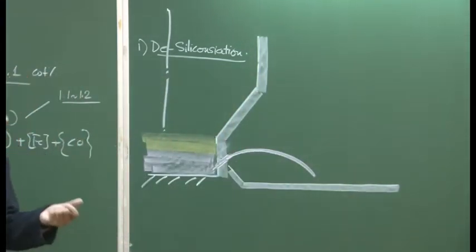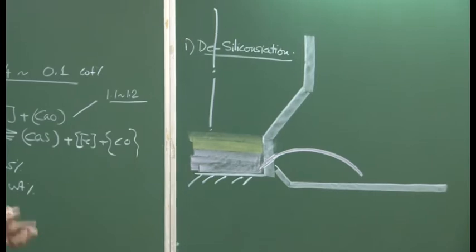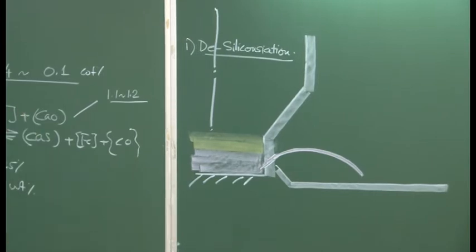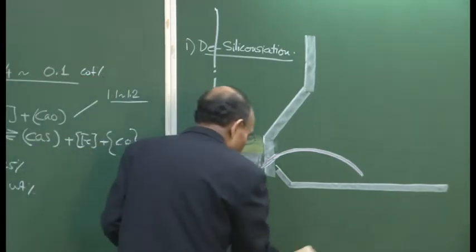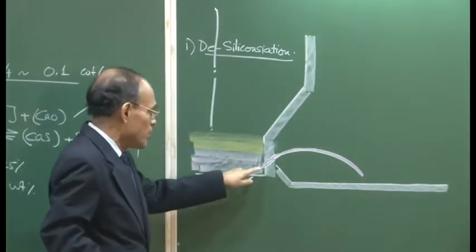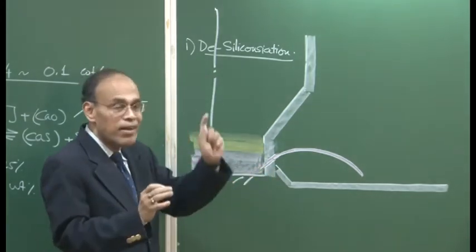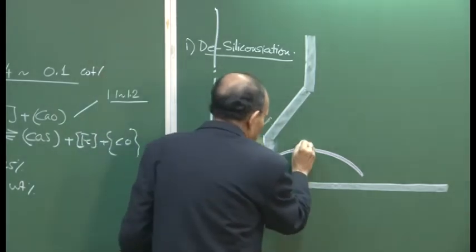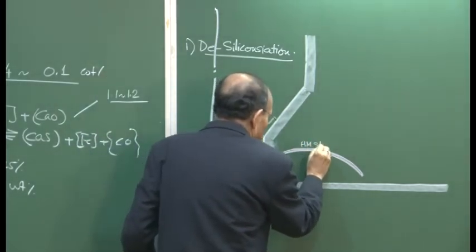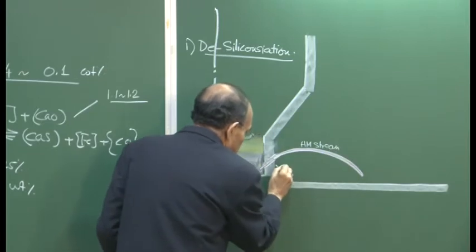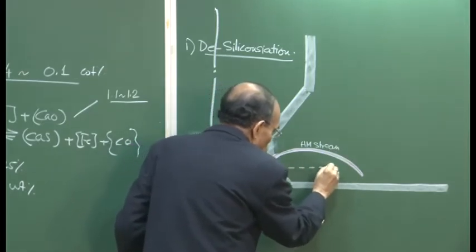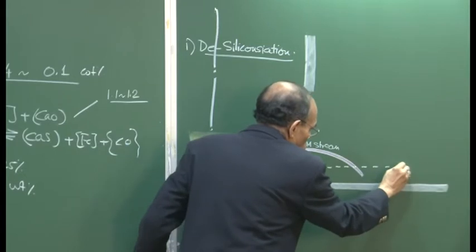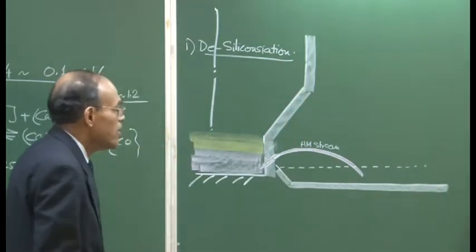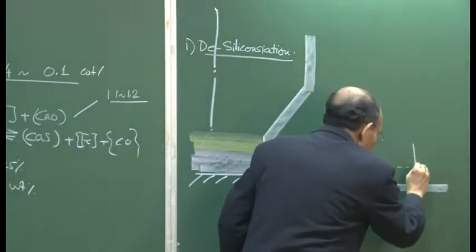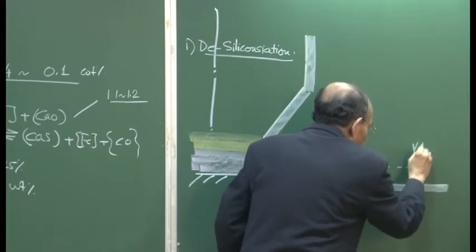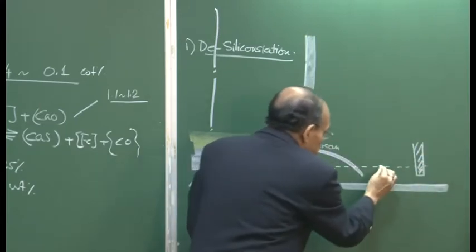It is put in ladles or in torpedo vessels, and then it is transported to the steel making reactor. So that is the hot metal stream. I have drawn this angle a little steeper, it is about 10 degrees tilted, and this is the hot metal stream. And this is the level, and we have a slag skimmer somewhere here, and the slag separates out here.